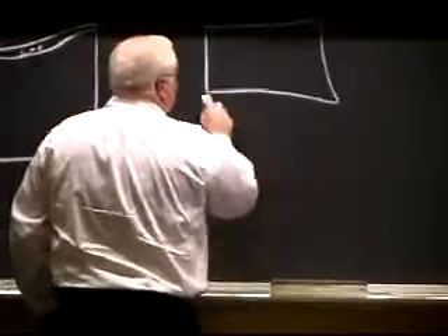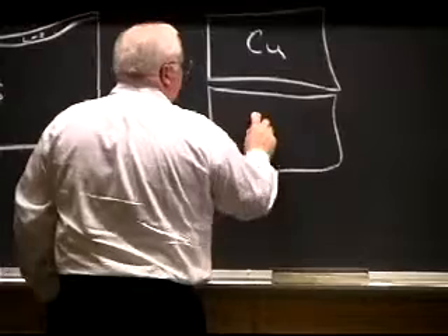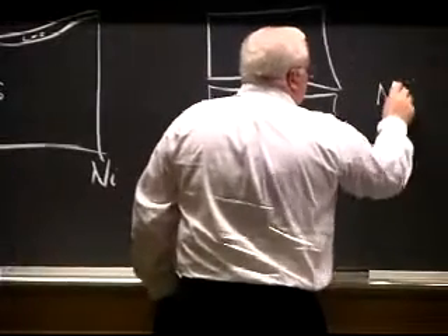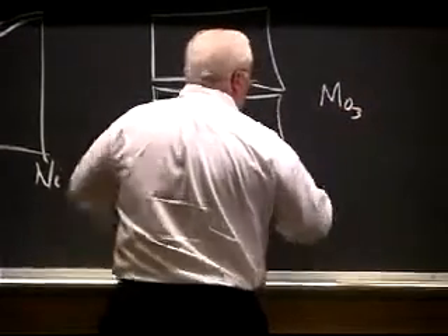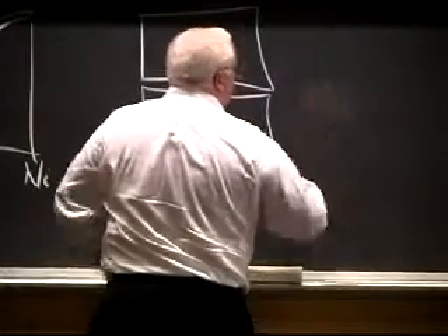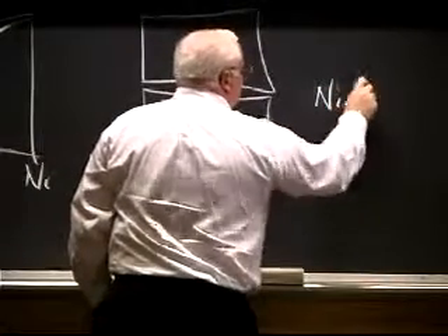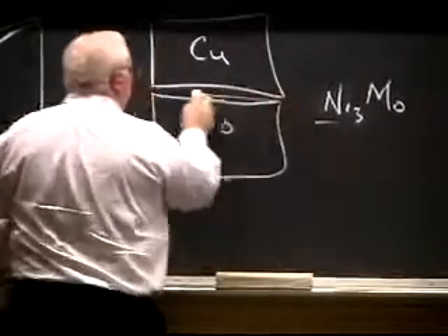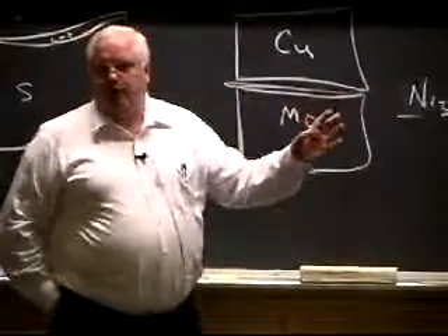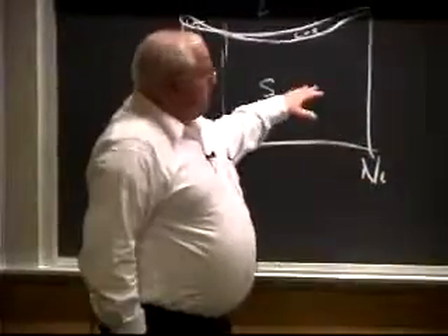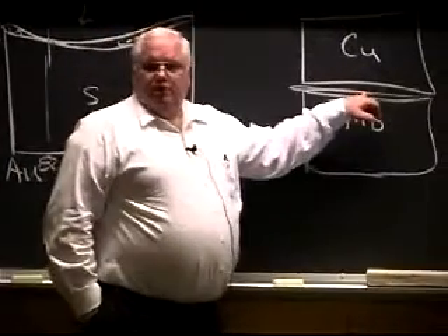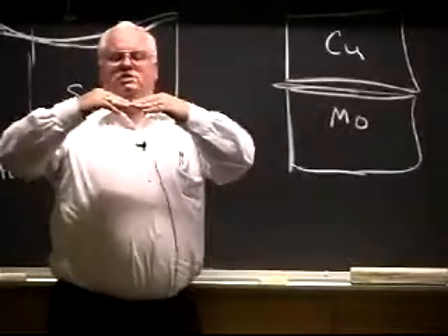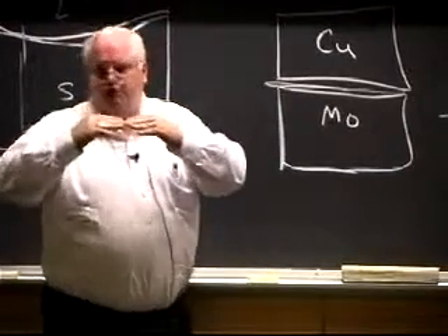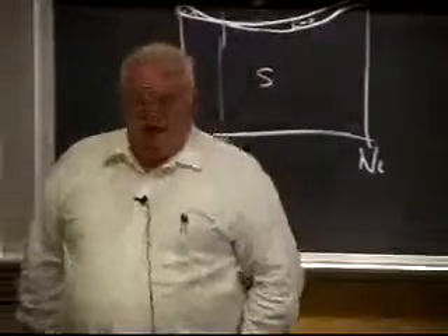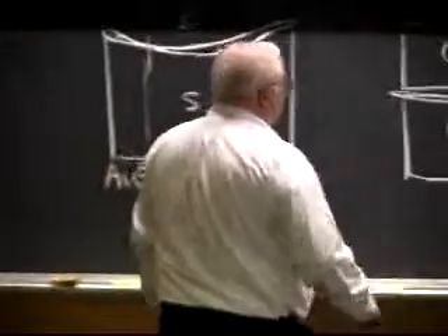The problem, if you've got a molybdenum copper joint with this braze alloy, is with 18% nickel, you've got copper up here, molybdenum down here. Molybdenum tends to form a nickel 3 molybdenum intermetallic that's brittle. And I mentioned before, one of the problems with diffusion bonding is brittle intermetallics. This is actually supposed to be a braze, and they were getting these brittle intermetallics, and so if you try to make one of these specimens and bend it, you get like a 5 or 10% bend before the molybdenum would just snap off. And that was a problem in terms of overall reliability.